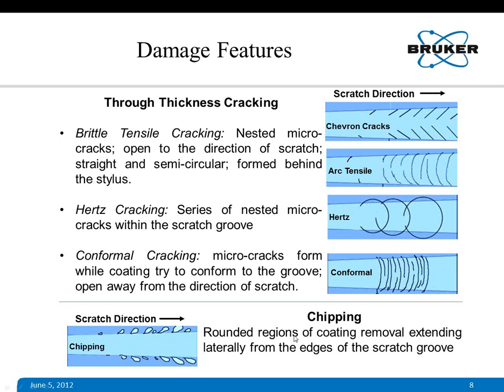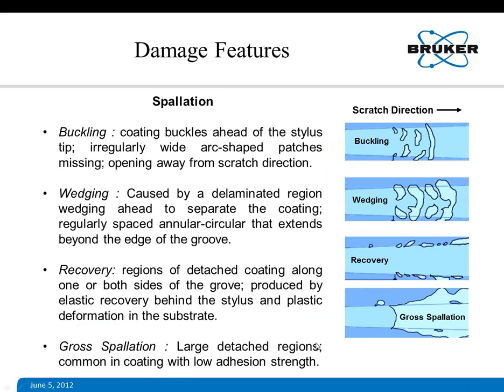The chippings are rounded regions of coating removal on the surface of this coated specimen, extending laterally from the edges of the scratch groove. Some other damage features related to adhesive failures are buckling, wedging, recovery, and gross spallation. These mostly happen due to compressive stress on the coating.